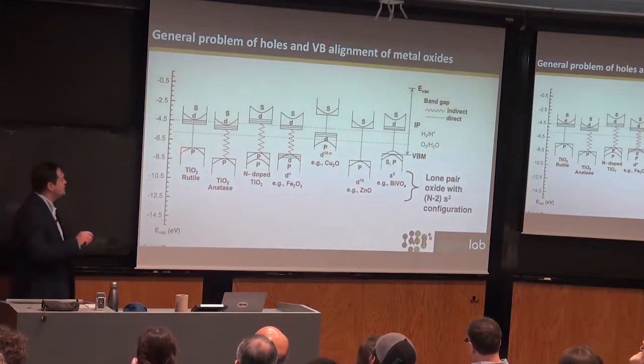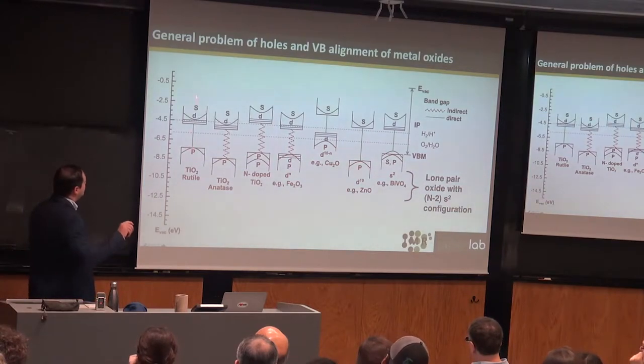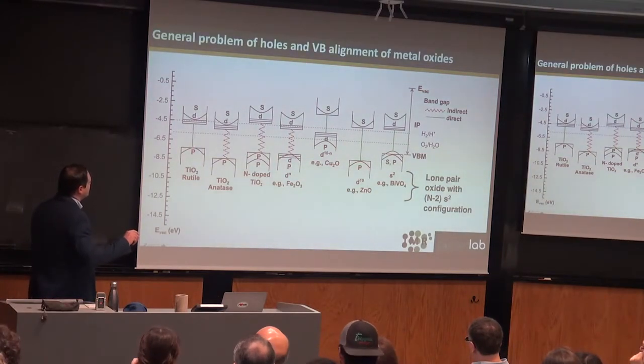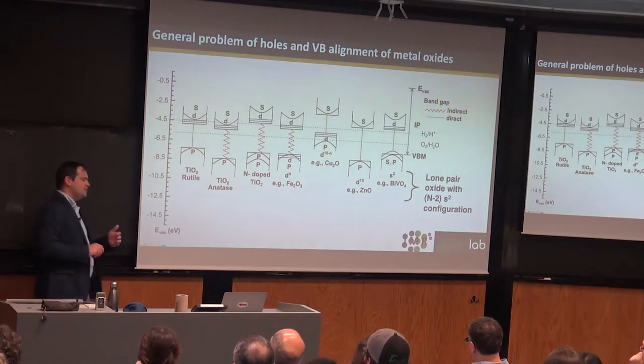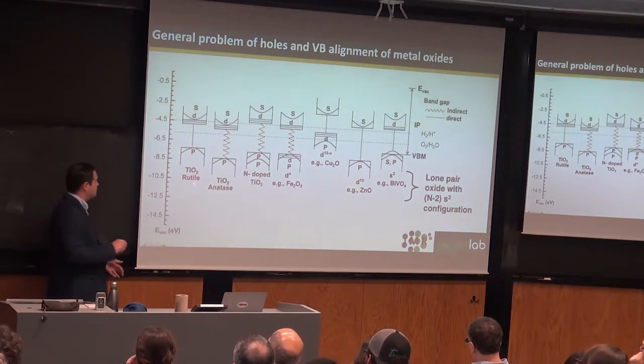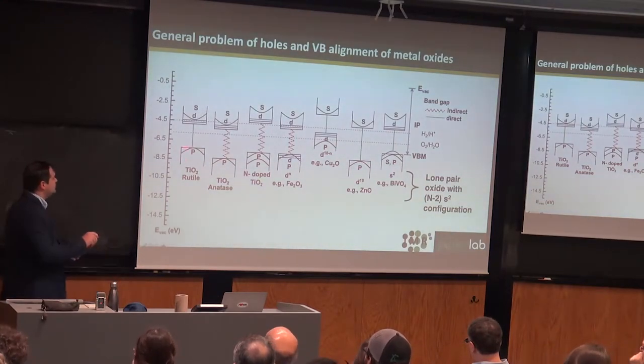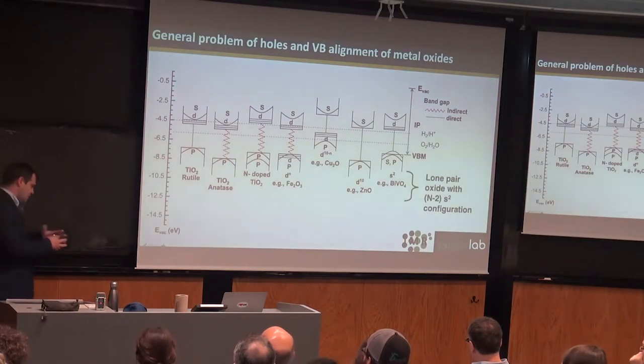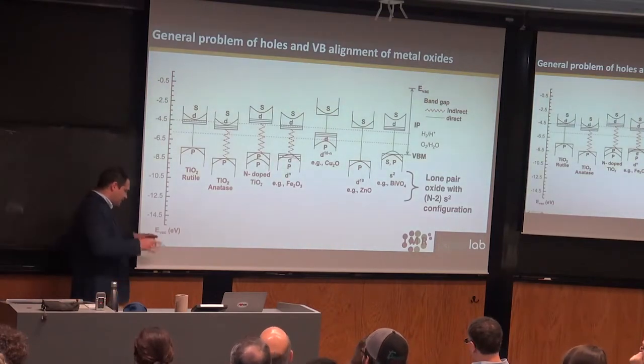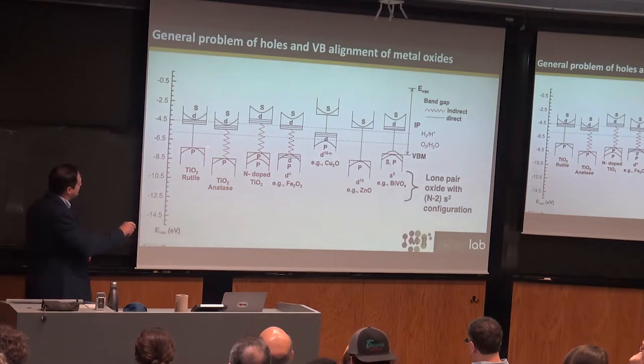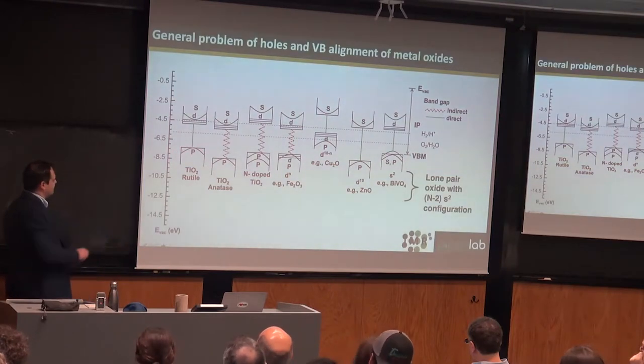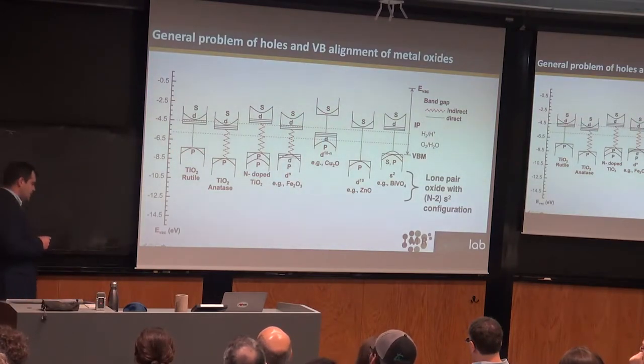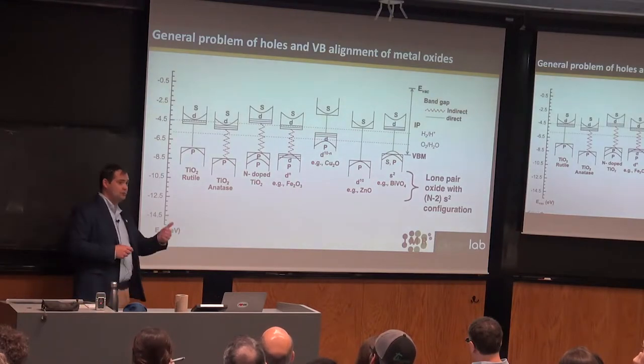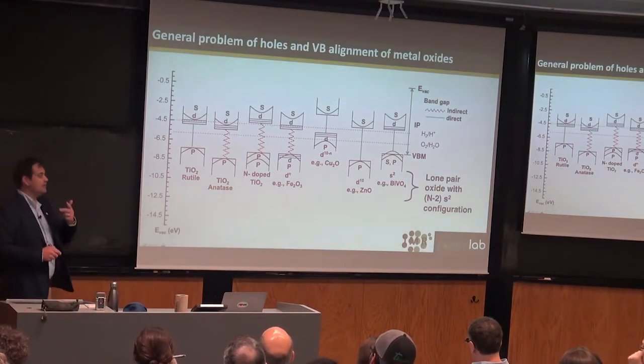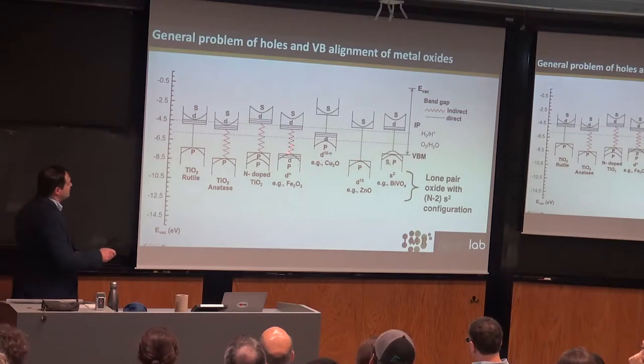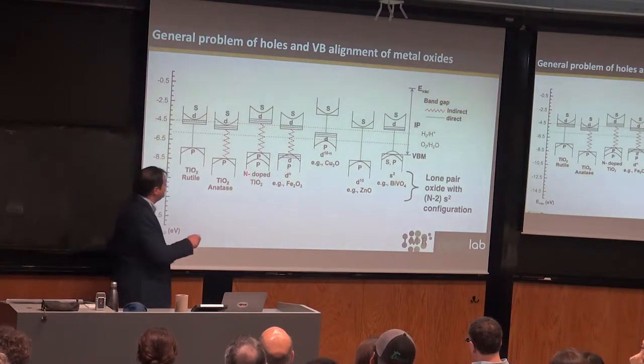And so the idea is this energy difference means it's unlikely to form holes to begin with, but once you do form them, because they're these non-bonding orbitals, they are very flat, and so, let's demonstrate it schematically like that. The idea is that they're not very mobile. So we want them to form readily, and we want them to be mobile, and we want the energies much higher. So the trick is to hybridize them with metals.